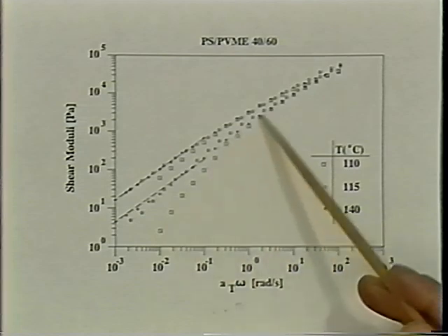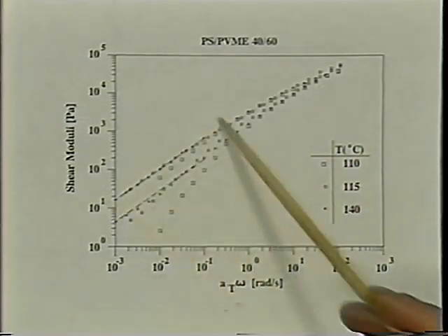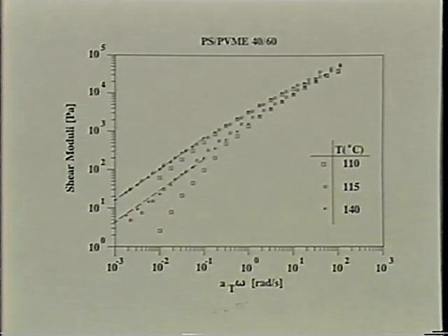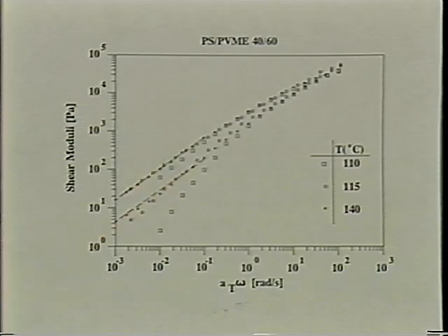For the liquid behavior, we have a broader, more extensive curve, but everything seems to be happening at very low frequencies. At high frequencies, the spectrum is not affected. Only the long times, the large-scale mobility, is affected by the phase separation. It's slowed down by the phase transition coming in, by the interface coming in. And that's really what we would be expecting.